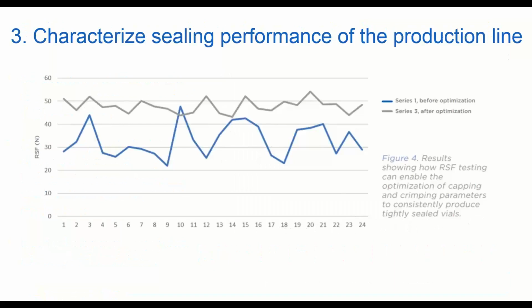Now we get to the other side of the coin, and that's characterizing the sealing performance of the production line. And what we're plotting here is some residual seal force data of a line before it was optimized and then after it was optimized. So the blue line there shows the RSF values that were measured on the non-optimized line. And you see that they're a little bit lower than what you would like, and they also have high variability. So going to your line and optimizing some of the capping and crimping parameters gets you to a situation which is plotted with the gray line, where the residual seal force value has gone up to an appropriate value, a little bit higher, and you also see that the variability is a lot less than before the optimization.